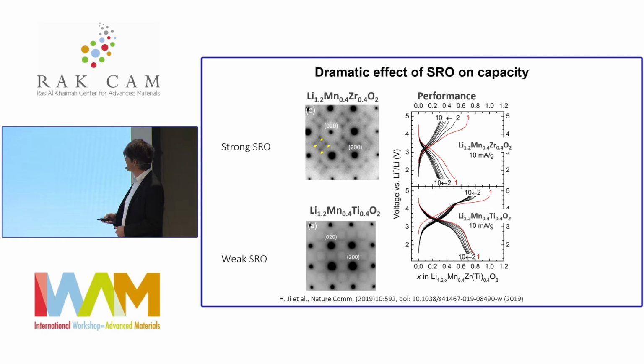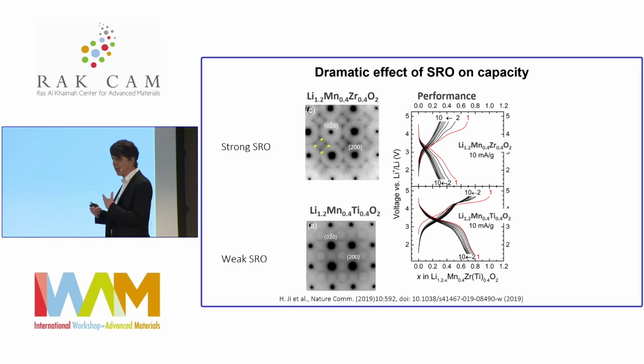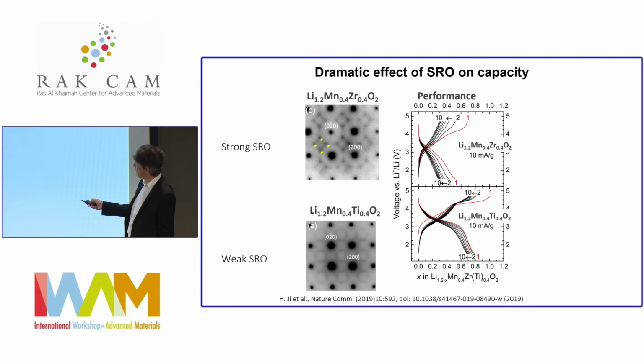Well, when we did the experiment, this is cycling data, and you don't have to know much about this except this is capacity. So you can see that the zirconium was much worse than the titanium. These were materials synthesized under exactly the same conditions, cells made under the same conditions. And what you see is that the zirconium one has very pronounced short-range order, to the point where this diffuse scattering is starting to sharpen up, meaning the extent of the short-range order is becoming pretty long, whereas in the titanium one, it's actually a little less diffuse.